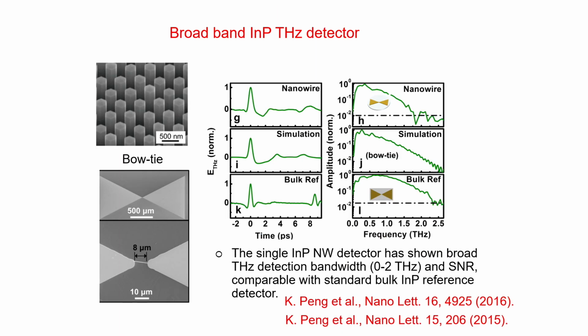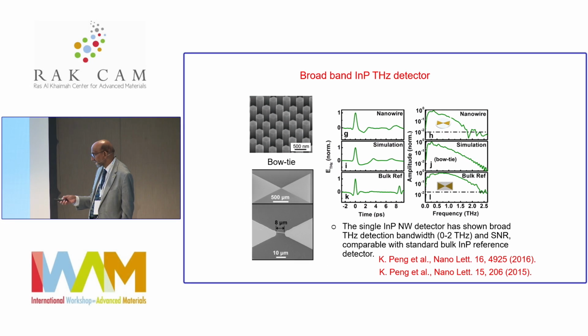To cut the long story short, we looked at gallium arsenide nanowire terahertz detectors and indium phosphide terahertz detectors. The challenge is to make good antennas to couple the light from a 300 micron wavelength into these nanowires, which are only about 300 nanometers in diameter and about 5 or 10 microns long. That means you need to couple the light, and that's where K. Peng has spent a lot of time.